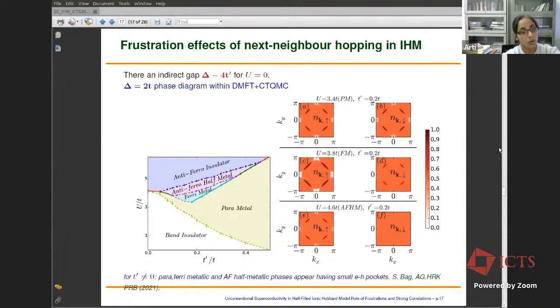In fact, there are no hole pockets now in the downspin sector. So this is the ferrimetal phase, where the net occupancy of the upspin is larger than the net occupancy of the downspin, but the neighboring spins are still antiparallel to each other. And then in the antiferromagnetic half metal phase, we see the Fermi pocket only in the upspin channel, and the downspin channel is completely gapped, resulting in an antiferromagnetic half metal phase.